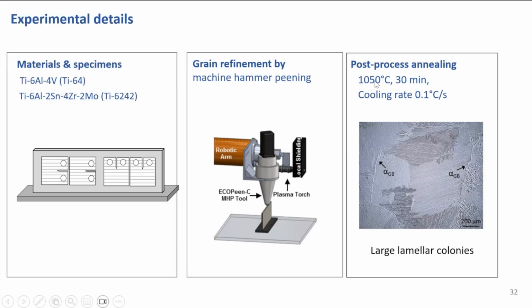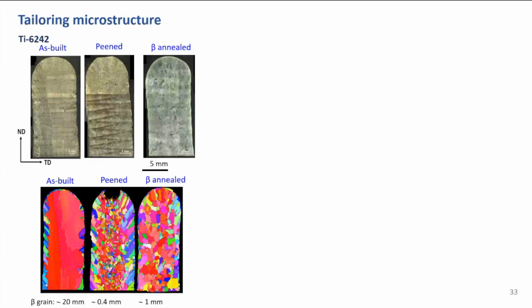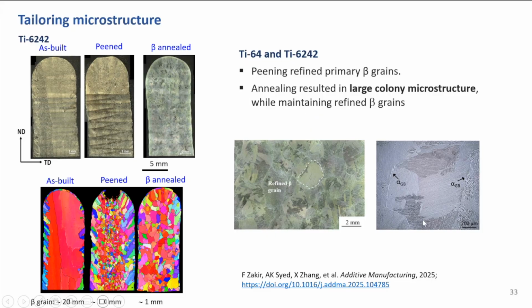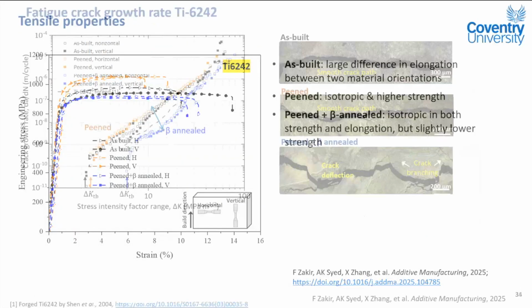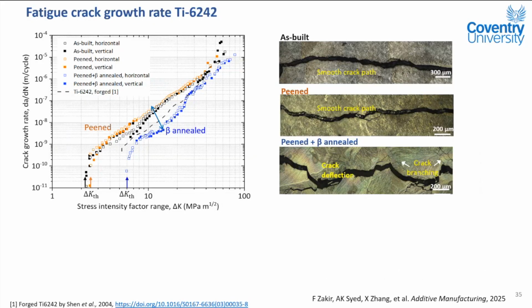After the beta annealing at this temperature, the microstructure becomes large lamellar colonies, which has a lot of resistance to crack growth. So before I show the crack growth, I just want to show you very quickly the optical graph on the top and the EBSD images at the bottom. The far left shows large columnar grains in the as-built condition. After pinning, they are equiaxed grains. Then after beta annealing, the grains grow to double size, from 0.4 mm to 1 mm, but still equiaxed. And then the good thing about annealing is to create large lamellar colony microstructure to have more resistance to crack growth rate. I skipped the tensile. I just want to show tensile did not even suffer by beta annealing.